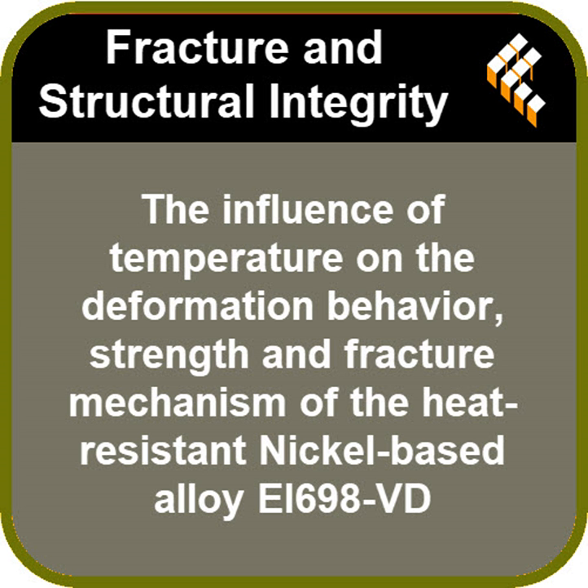Which is a complete disaster in an aerospace alloy. The allowable limit for lead in this material is what? Less than 0.0001 percent. It's incredibly strict. But this batch... This batch had 0.09%. Yeah. 900 times the acceptable limit. A catastrophic quality control failure.